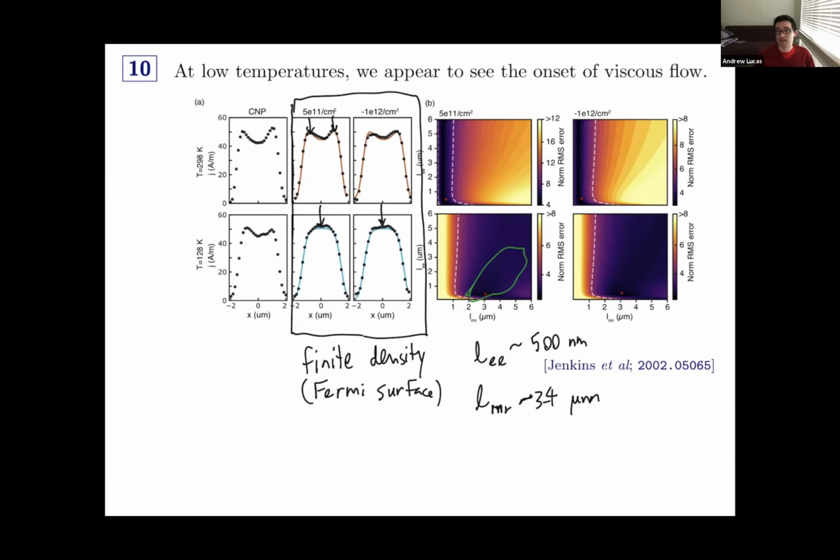Like if you have an impurity that happens to be close to this constriction. Graphene has Coulomb impurities, they're pretty sparse, but if you have one near the constriction, it's just going to ruin the whole image, because you're going to see that impurity warps the current profile. And so to pattern a complex device many, many times over until you get lucky with where your impurities are, that's not an easy experimental task. In the future, we'll probably be better with it, but that's one reason why it wasn't done the first time.